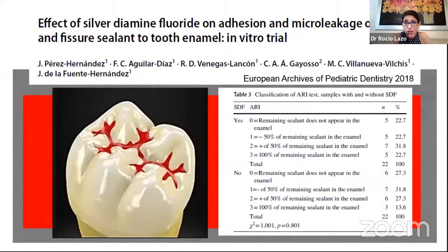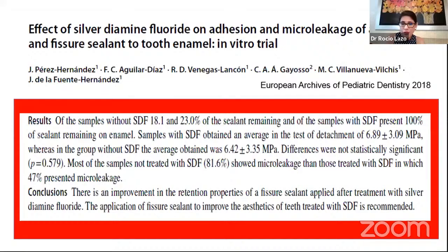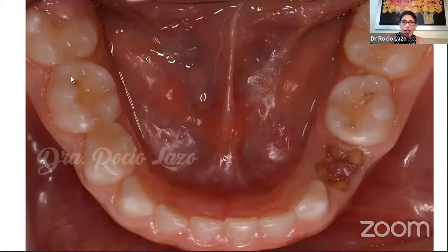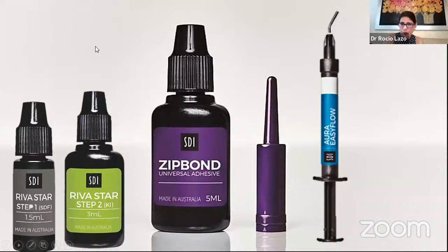We can use the SMART technique with sealant. Yes, the SMART technique is not only with glass ionomers. The SMART technique is first SDF and then you apply any adhesive material. It can be glass ionomers or maybe sealants or resins, and you will have good results. For example, in this case, this is an enamel caries, and I prefer to use the SMART technique with a flow resin. First I apply the SDF, then the KI, and after the KI, I dry and apply the universal adhesive.